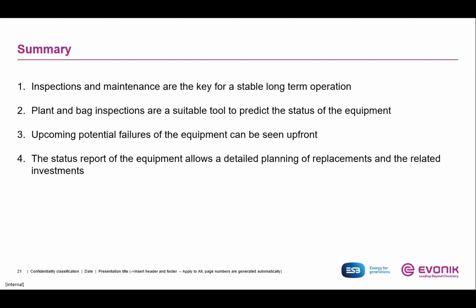And of course, a steady plant operation and also inspection, because one broken bag must not cost too much, but it can ruin a lot of other bags by the so-called cross-contamination, when dust is coming through this broken bag and blown into other bags. So follow-up failure rate is something that can be prevented when you talk about preventive maintenance. And of course, do some external tests, because you cannot determine the condition of the filter bags by just watching the performance on the PLC systems. You can really have a good idea about the current status of the bags, and this will help you a lot in planning further maintenance of bag exchange before things even happen.